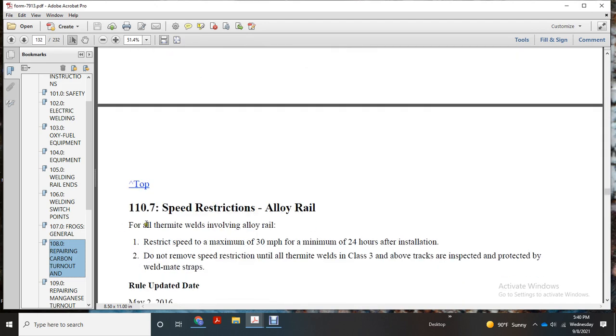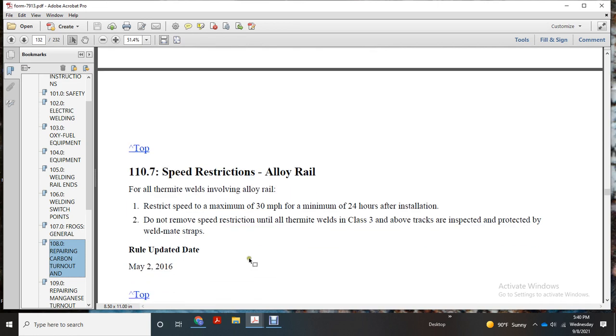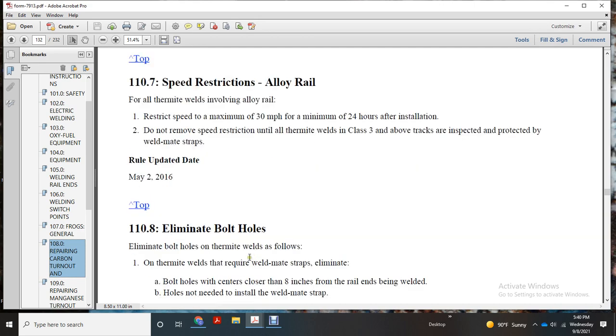Speed restriction for alloy rail: for all thermite welds involving alloy rail, the restriction is a maximum of 30 miles an hour for a minimum of 24 hours after installation. Do not remove the speed restriction until all thermite welds in class 3 and above track are inspected and protected with weld mate straps. Eliminate bolt holes.